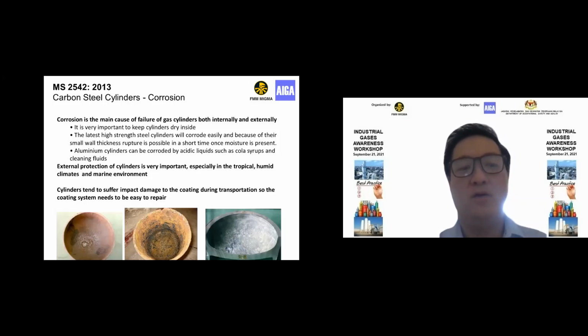Okay. Aluminium cylinders, although good against moisture, need care against acidic liquids, such as cola syrups, like Coca-Cola, backflowing into a cylinder and mixing with the CO2 gas itself. It creates carbonic acid that causes internal corrosion. Some photos below show internal corrosion. The bottom two are due to moisture ingress, and the right one is on an aluminium cylinder due to carbonic acid corrosion. Okay, next.